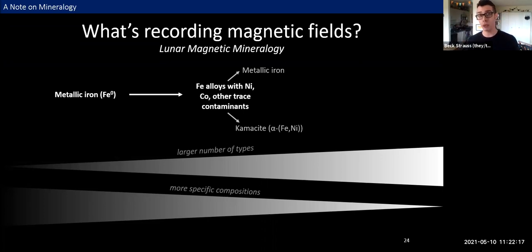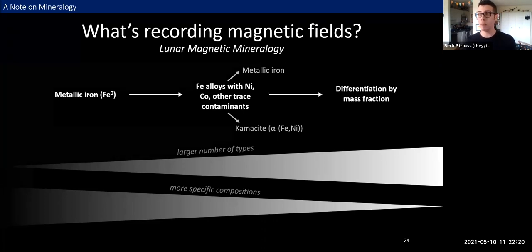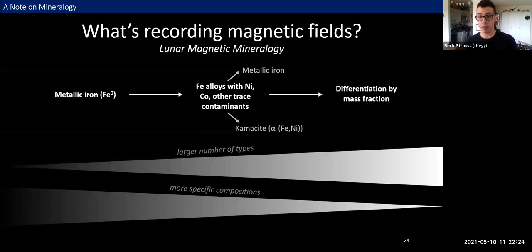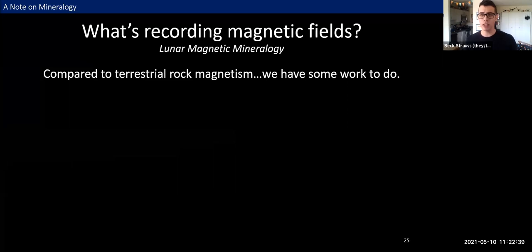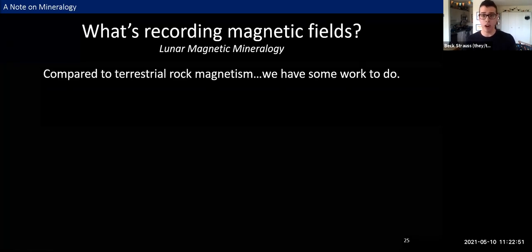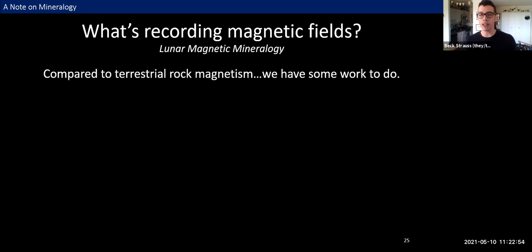Now, over the past decade or so, improved methods for the assessment of paleomagnetic fidelity have been accompanied by more detailed analyses of magnetic carrier minerals, including non-magnetic analyses that let us differentiate iron nickel alloys by mass fraction. For instance, we can now tell kamacite, which is a low nickel alloy, apart from taenite, which has a higher nickel content. So if you're familiar with terrestrial paleomagnetism at all, you're probably already realizing that lunar paleomag has a little bit of catching up to do. Although various magnetic parameters in lunar rocks have been surveyed to varying extents, including hysteresis and susceptibility, we're still kind of working on modernizing our approaches to experimental methods and the strategies that we use to interpret magnetic characterization data.